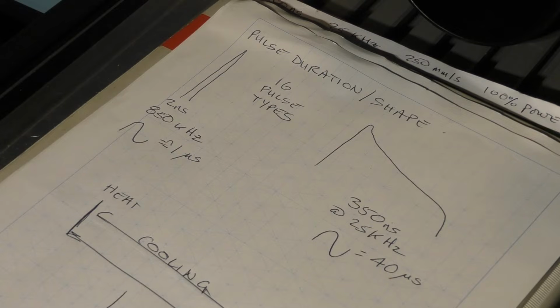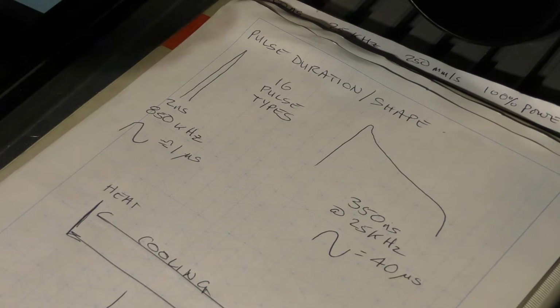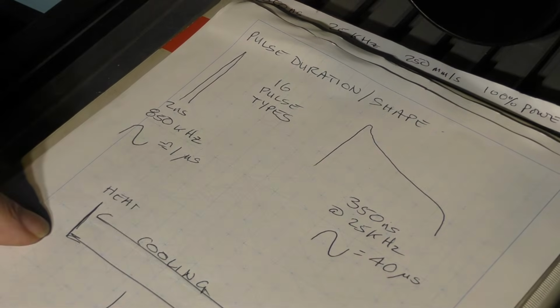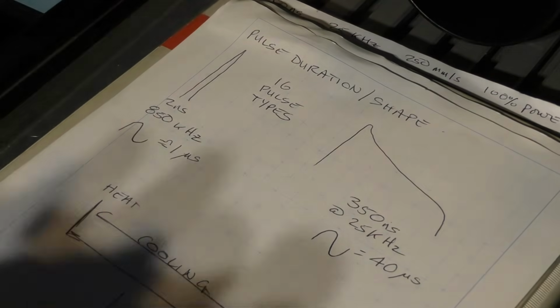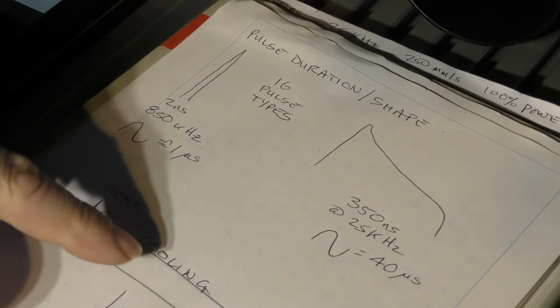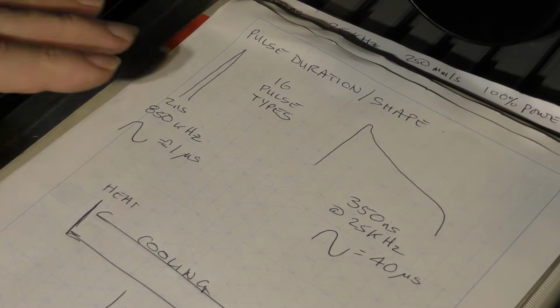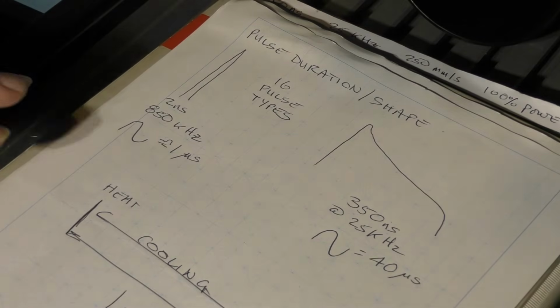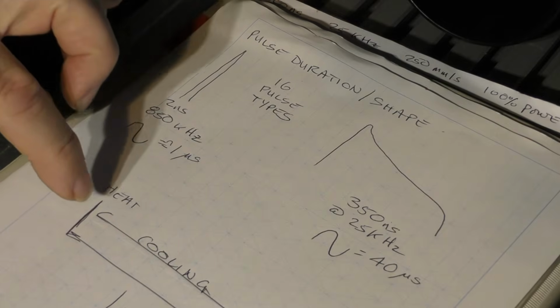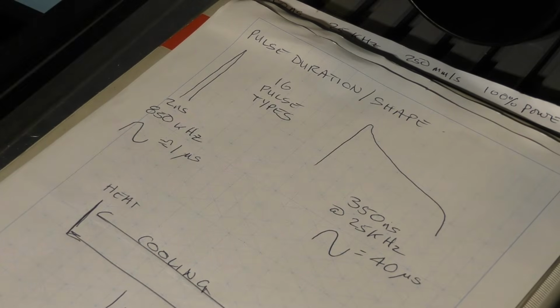How on earth are we ever going to get any heat into this product? Well, the answer is really because of the thermal reactivity of the material itself. The material cannot cool this quickly. It can heat up, and eventually, if you heat it enough times in the same spot, it will get hotter and hotter because it does not get a chance to cool in between the pulses. Now, that's an important fact to remember, that if we can put more heat into the same spot, we will gradually raise the temperature of that spot.